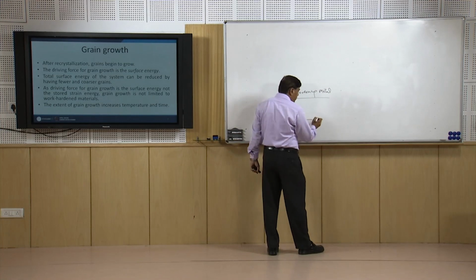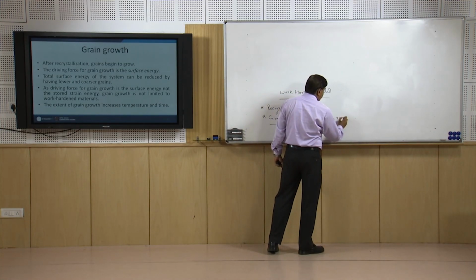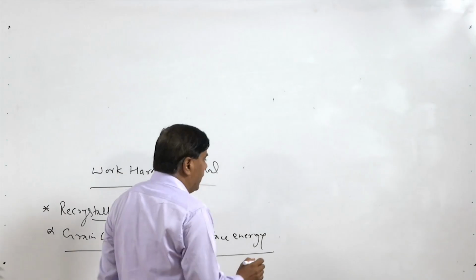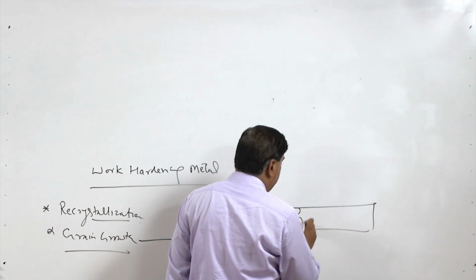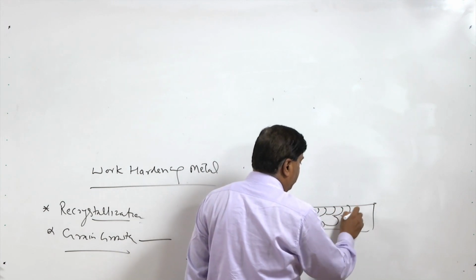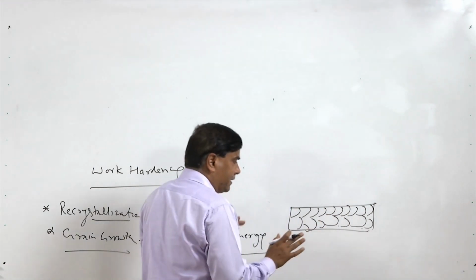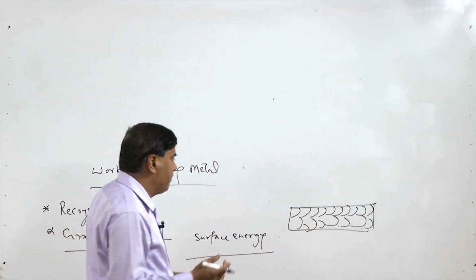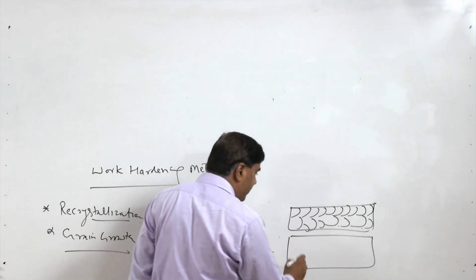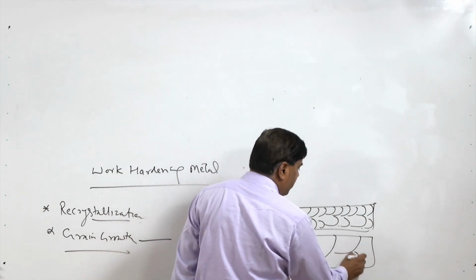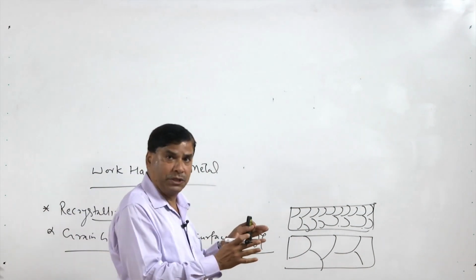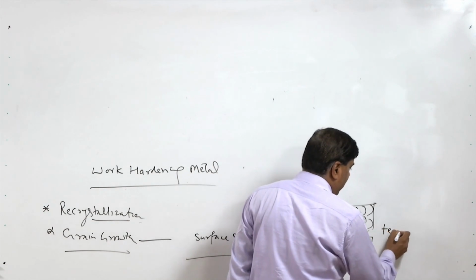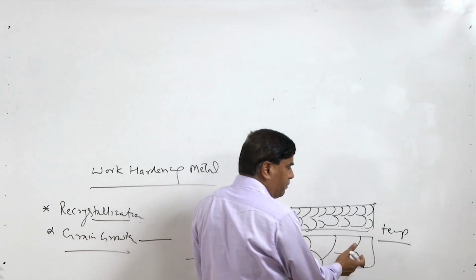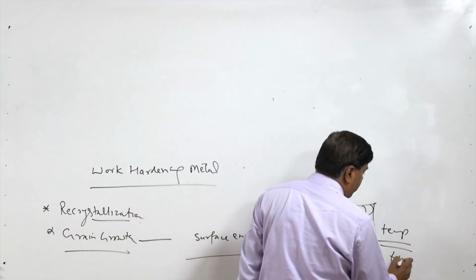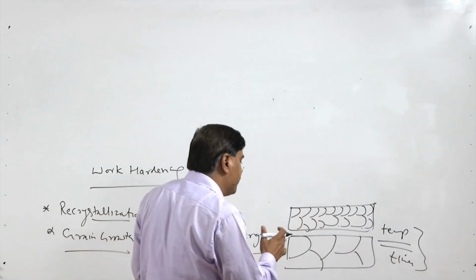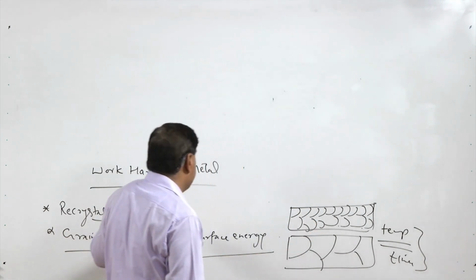The driving force for grain growth is the surface energy, not the strain energy like in recrystallization. Most metal systems are made of a large number of grains; the more the number of grains, the larger the grain boundary area, and the greater will be the surface energy associated with it. So, all metal systems try to attain the minimum energy for maximum stability, and therefore metal systems under favorable conditions tend to attain a larger grain size, so that fewer grain boundary area helps to reduce the surface energy associated with them. So, for this purpose what is needed? High temperature, since this process is diffusion dependent. So, it needs enough temperature and time, so that diffusion can facilitate the change in grain size for the maximum stability of the system.